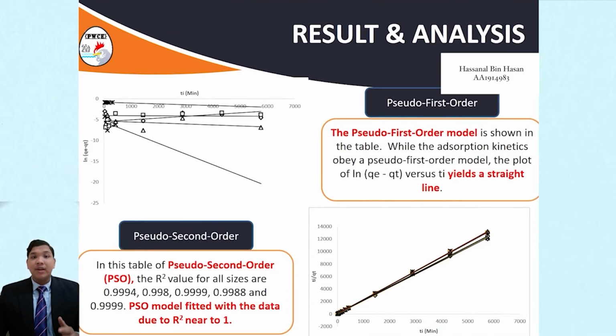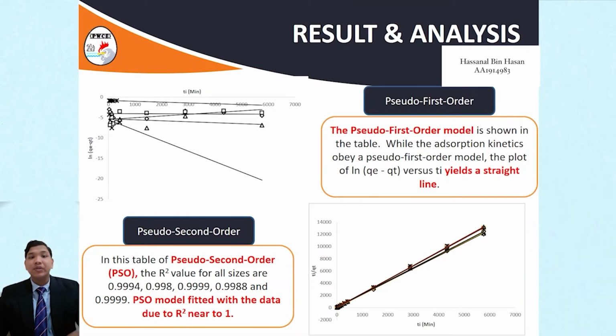Next, in result and analysis, there are also pseudo first order and pseudo second order models. First, the pseudo first order model is shown in the table, while the adsorption kinetics obey a pseudo first order model. The plot of ln(Qe minus Qt) versus t yields a straight line. Second, the other model is pseudo second order. The R2 values for all sizes are 0.9994, 0.998, 0.9999, 0.9988, and 0.9999. The PSO model fits the data because R2 is near to 1.